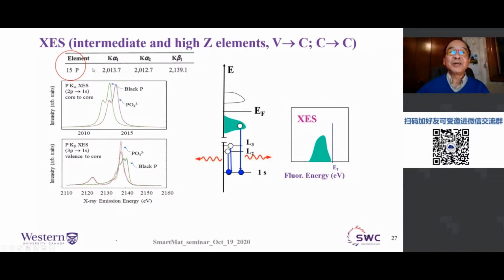Phosphorus fits this situation because the 1s core hole has some 2p states above it, before the valence band, right? So the core hole can be filled by this shell as well as by the valence band. If it is filled from the core, then between two different compounds, say phosphorus in the 0 oxidation state and phosphates in the 5 oxidation state, all you see is a similar feature, but with a chemical shift due to the difference in oxidation state.